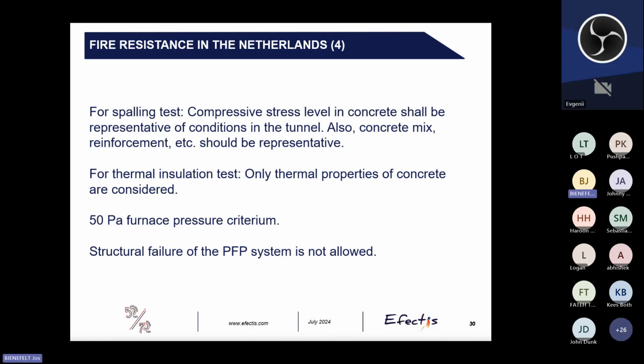For the spalling test, a compressive stress level should be maintained, which is representative of the conditions in the tunnel, because those have a negative influence on the spalling behavior of the concrete. But also the concrete mix, reinforcement, etc., should be representative of the actual situation. And for the thermal insulation test, only the thermal properties of concrete are considered. So in this case, there is a furnace pressure criterion of 50 pascals. And again, structural failure of the PFP system is not allowed.